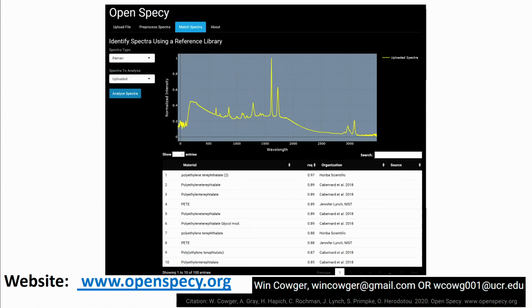And here's an example. Last night, I uploaded a polyethylene terephthalate spectrum that I generated from a consumer good that had the resin code number 1 stamped on the bottom of it. I collected this in Raman. And you can see the top 5 hits there are all polyethylene terephthalate, and they came with very high match scores above 89%. And it actually hit out of at least 3 different libraries, one submitted by Horiba, one submitted by Cabernard et al. 2018, which I believe is out of Sebastian Primpke's lab, and a library that came out of my lab.